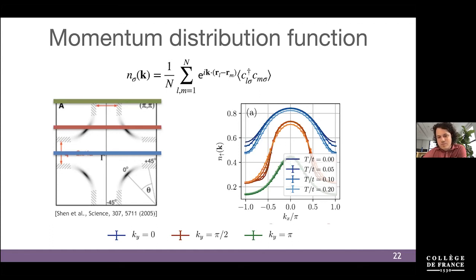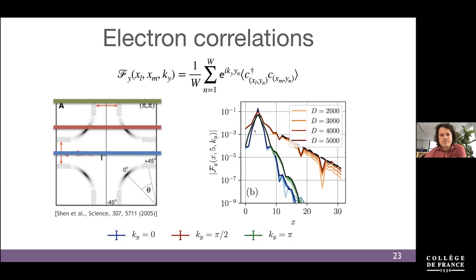What we observe is that the slope in the momentum distribution function is steepest close to the red line, which is this line here, and it's steepest close to this nodal region. This indicates that the gap is smallest close to the nodal region in the single-particle function. We see the slope is much smaller here, which is the first indication that the gap might be larger at the boundary of the Brillouin zone. Also, in the blue line we don't see a big slope, which indicates a large gap in the single-particle excitations. One can also look at this a little bit differently. One can look at the Fourier transform of the electron correlation, and we Fourier transform them only in the y direction of the cylinder.